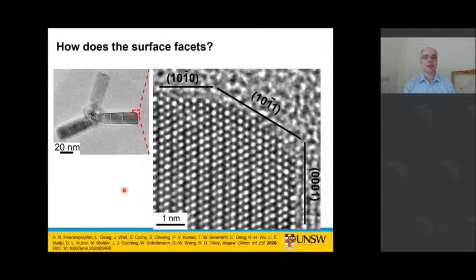And again, we can do our high-resolution electron microscopy. As I said, we have these nice, sharp, straight edges, which is what we're after, and our sharp, straight edges at the end of the particle. And we can do our indexing of our high-resolution electron microscope image. And again, this is a nice picture in terms of seeing the A-B stacking that you get from a HCP structure. You can see how the diamonds look going across, and then we can index and see that we get our low index facets again from our structure.